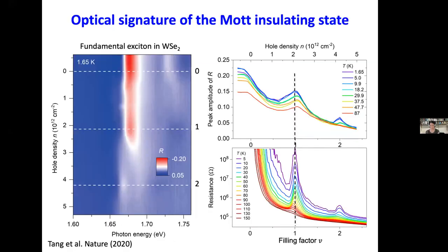Okay, so we've already seen that the in-plane electrical transport can give you a signal of the Mott state. And interestingly, we can also observe this state using optics. So what I'm showing in the top panel is the peak of the exciton absorbance as a function of filling. And then you can see the two bumps here. One corresponds to a band insulator, and the other one corresponds to the Mott state.